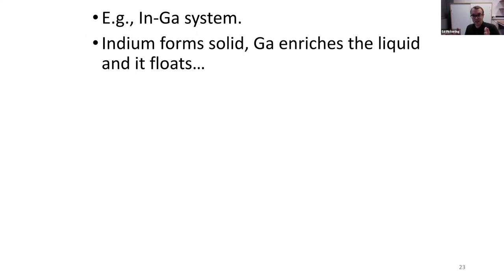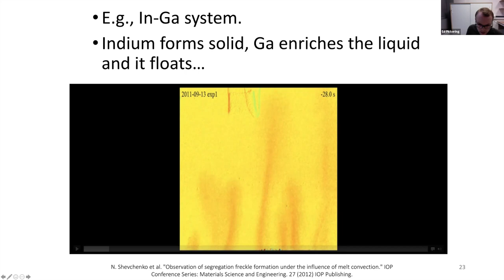You can't really do it on steels because it's not transparent to X-rays enough. But anyway, in this particular radiograph, a set of radiographs in real time, indium forms the solid in this indium gallium alloy and gallium enriches the liquid and it floats because it's the lighter element. So what I'm going to show you here, and this is the reference for this beautiful work down here, is this happening. So what you can see here is it's actually being solidified directionally from the bottom.